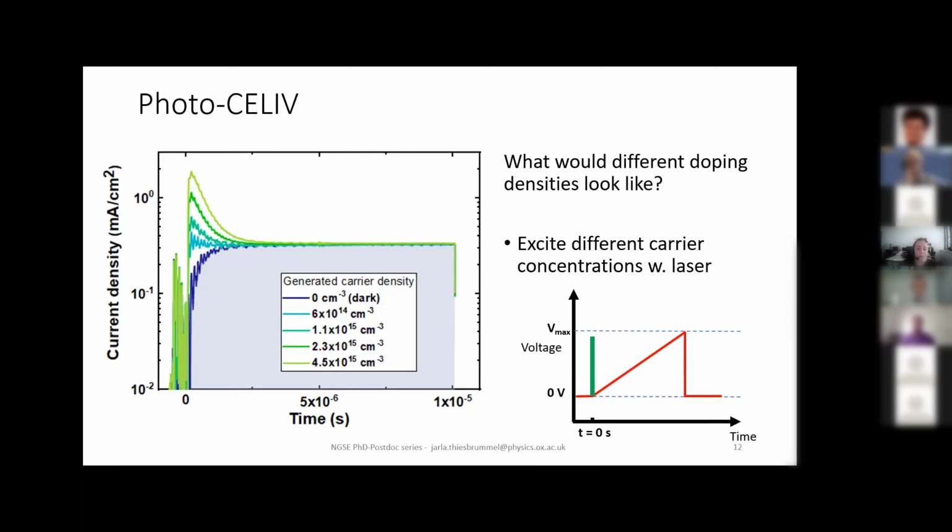All right, so basically now for these lead-tin perovskite solar cells, we figured out that mobile ions are causing transient current losses and the doping is probably not causing any of these transient losses.